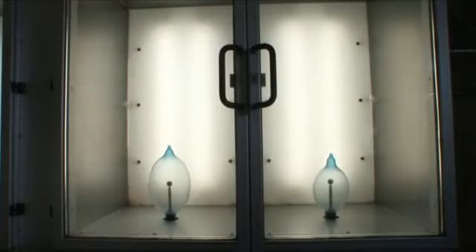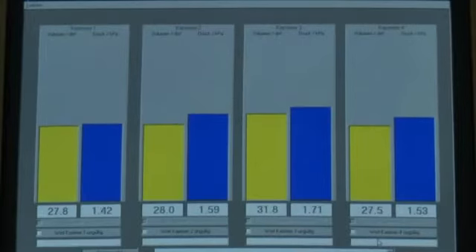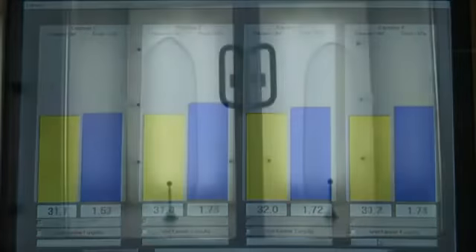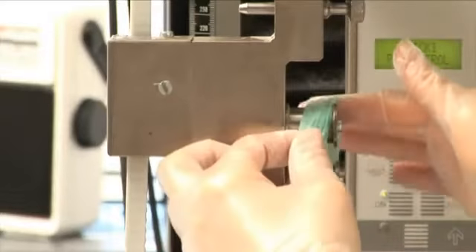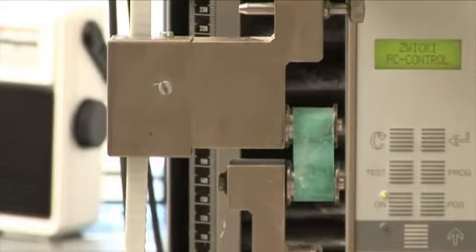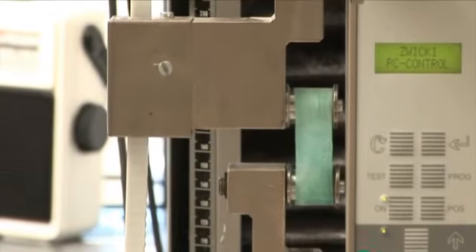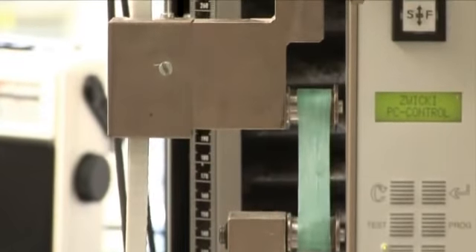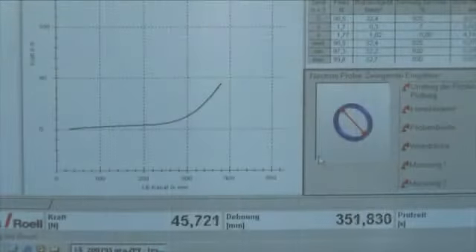Thus, the international standard ISO 4074, for instance, requires that spot checks are made, ensuring that the bursting volume of a condom after an artificial aging process, respectively until the actual expiration date, must amount to at least 18 liters. All MAPA quality condoms exceed this threshold by far. The second test of these spot checks examines the condom's stretch resistance. Here, stretch coefficients of 700% and more of the original coefficient must be reached.